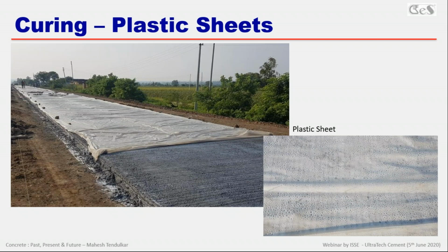Just imagine there is a concrete surface, we put plastic sheet, and water from concrete. This concrete will start hydration. This is an exothermic reaction. Because of that, water will be heated and will try to come out from the concrete surface. But because of this plastic sheet, it will condense. So all these water vapors will be condensed, and you can see droplets within a few hours or even half an hour beneath the plastic sheet. So we are improving the humidity level beyond 90% between the concrete surface and the plastic sheet.